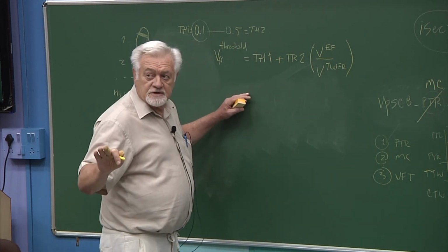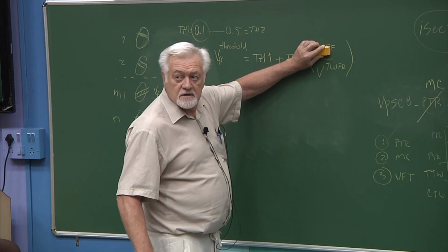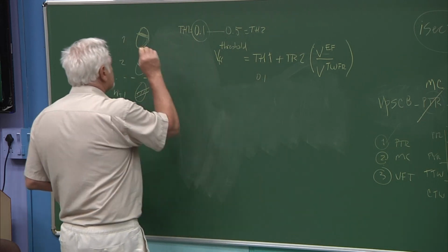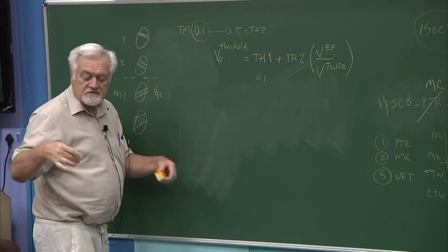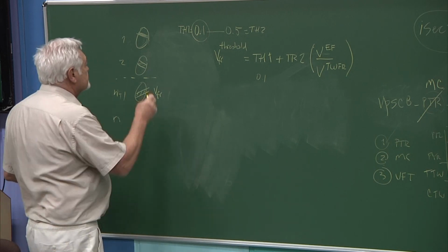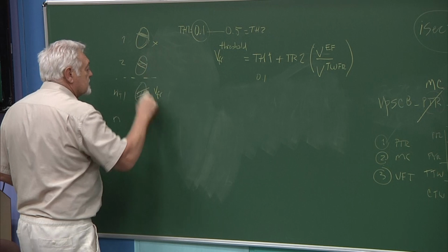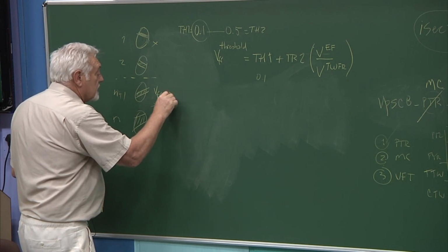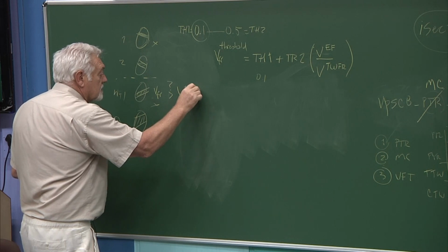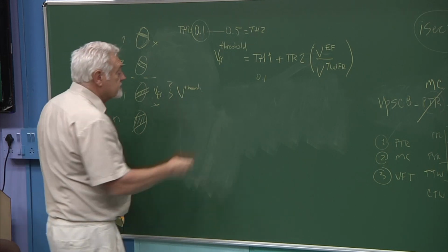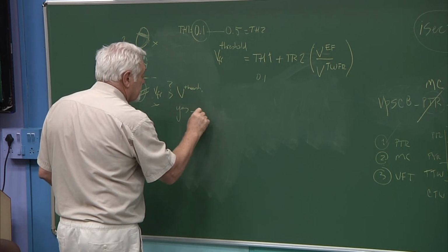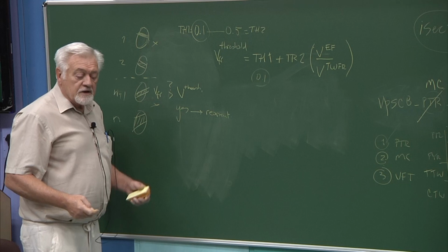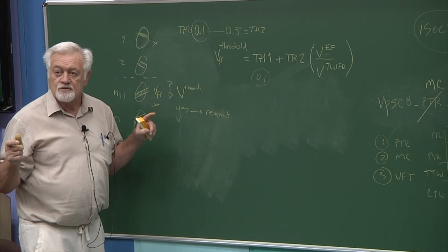So at the beginning of the formation, you haven't reoriented any grain, so this is 0, okay? And this number is going to be 0.1. Then you go and you sample all your grains, your 500, 1000 grains, whatever. You sample them randomly and say, okay, maybe you pick this grain and you pick this grain, for example. And you say, is this volume fraction larger than the threshold? So if the answer is yes, then you reorient the grain. And the threshold at the beginning is 0.1. So it has to accumulate at least 0.1 of the volume fraction of the grain to qualify. Okay?